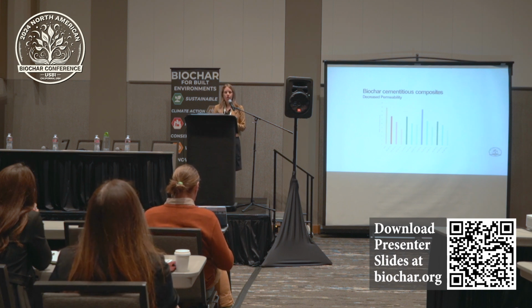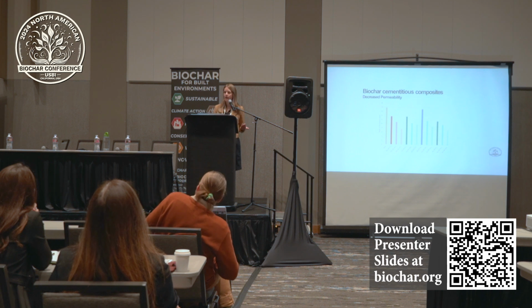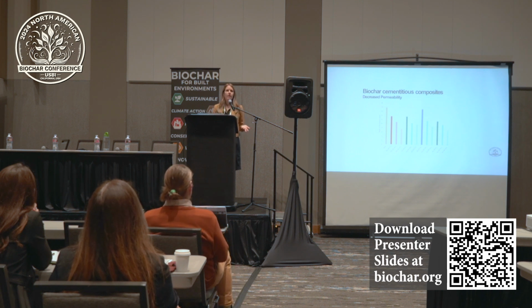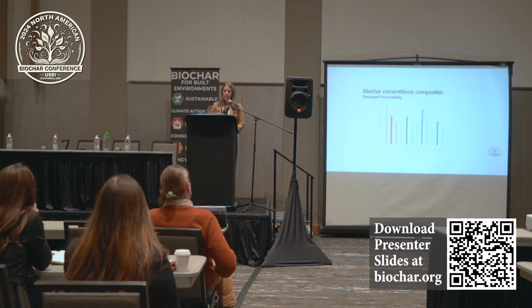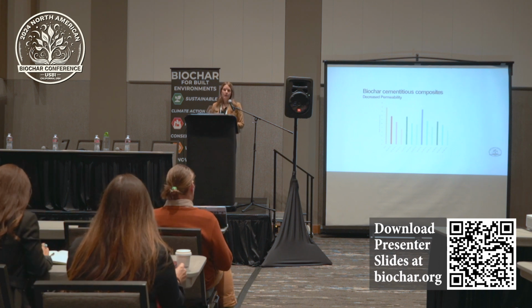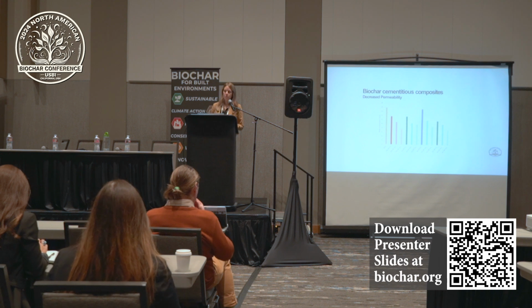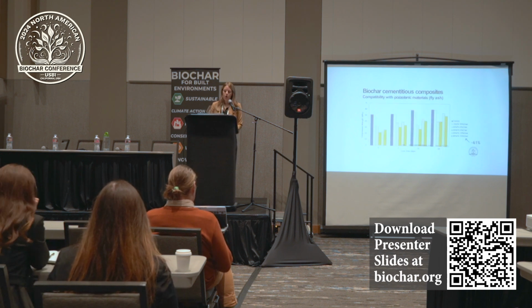Almost all the ways in which concrete fails is due, at least in part, to water ingress inside the concrete. So if we can make it less permeable, then it should be more durable as well. So this is great news in that we can anticipate that the biochar cementitious composites will also be more durable. We've also done some testing to see how compatible it is with other commonly used mixtures like fly ash.